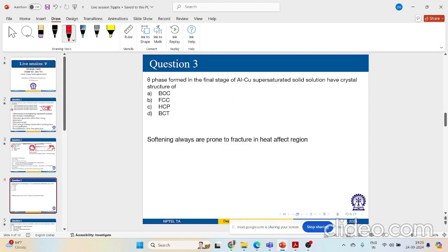Next, we talked about the precipitation hardening of aluminum alloy. The theta phase formed in the final stage of the aluminum-copper supersaturated solution will have a BCT crystal structure. So, the supersaturated solid solution.